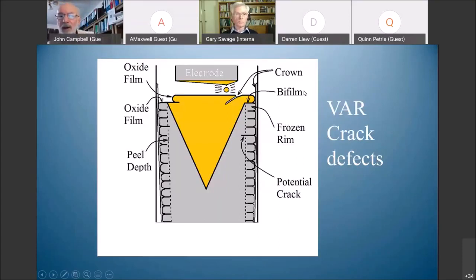I'm moving on now to talk about helicopter failures. And in particular, I'm going to talk about vacuum arc remelted steels, VAR steels, the most expensive steels you can buy, the most difficult, long-winded, extended process known to mankind. Anyway, you start with an electrode up here, you pass a big current through it, it melts the tip of the electrode drop by drop into an ingot down below, which solidifies. But as it solidifies, we get cracks.